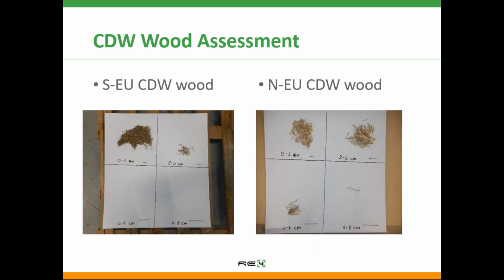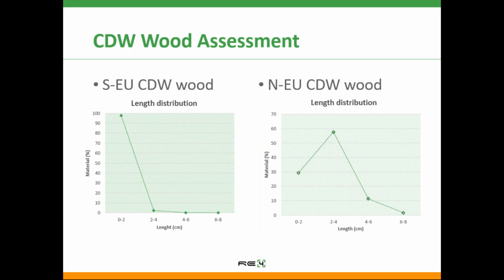The second characterization method is reported in the picture. A manual sorting of the particles has been carried out, separating particles as a function of the length. This work was aimed to define the typology of particles present in the wood fraction, for instance chips, fibers, wood wool, and their range of length. Four different classes of length have been used for the characterization: 0 to 2, 2 to 4, 4 to 6, and 6 to 8 centimeters. The difference in the graded classes is due to the choice of using a 20 mm mesh for grinding the Southern Europe material.